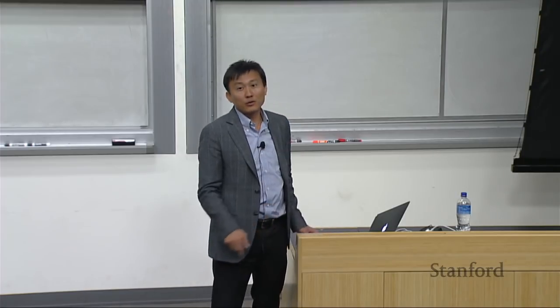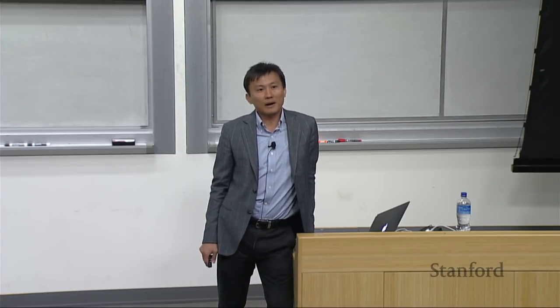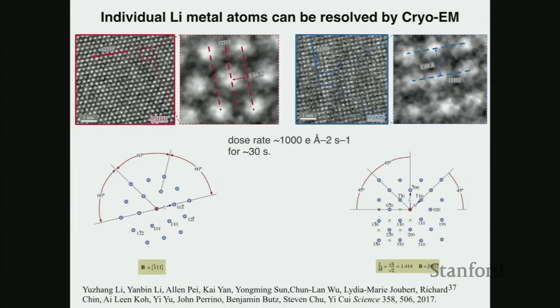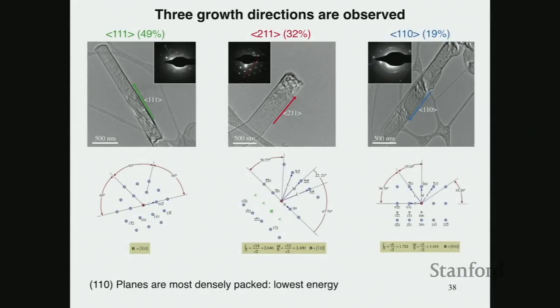This is a very exciting image. When my students showed it to me, I said, wow, this is just amazing. This is the first time anybody can see an atomic scale image of metallic lithium. Lithium metal has a melting point of only 180 degrees C. The bonding between lithium atoms in metallic lithium is very weak. So now it's possible to look at this atomic scale resolution. And now we can even look at along which direction crystallographically metallic lithium can grow. This allows you to study the growth habit, eventually providing information to solve the lithium dendrite problem.